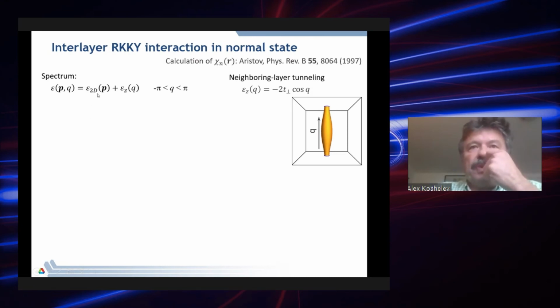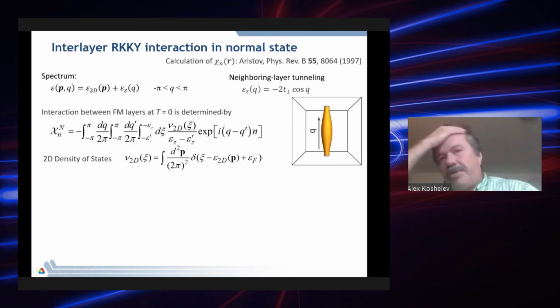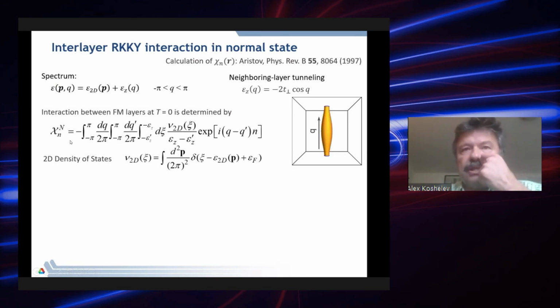So I consider a simple spectrum, a two-dimensional spectrum, and a c-axis spectrum caused by tunneling. Then it's possible to derive a very useful expression relating the interlayer susceptibility with the two-dimensional density of states.